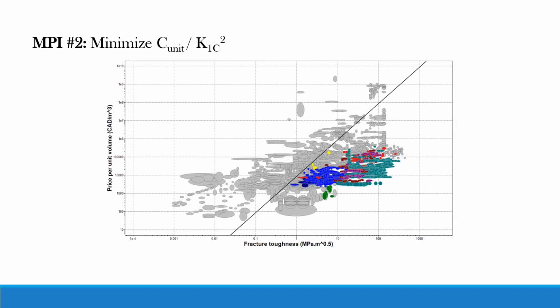This continued to reduce the number of materials available, and by developing an equation for the fracture toughness in terms of the maximum thickness of cracks, as well as the previous cost function, we were able to develop a second MPI where we defined this as the cost per unit volume measured against the fracture toughness of the material squared.